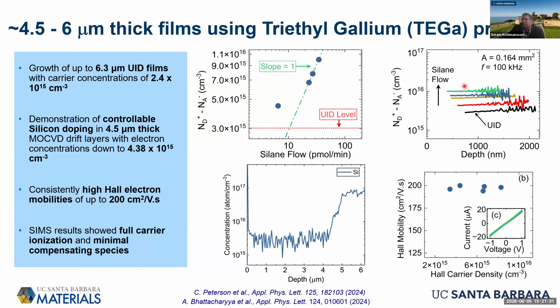And you can see this nice variation of the doping profile as we go to higher and higher silane flows. We've also verified that the source of electrons in this film is actually the silicon that we have in the film. So we've been able to make a one-to-one correlation between the measured electrons and the silicon measured from the SIMS, or secondary ion mass spectroscopy, measurements. And we've been able to get record electron mobilities close to 200 centimeters squared per volt second for the low doping range, all the way from 3e15 to the 1e16 range.